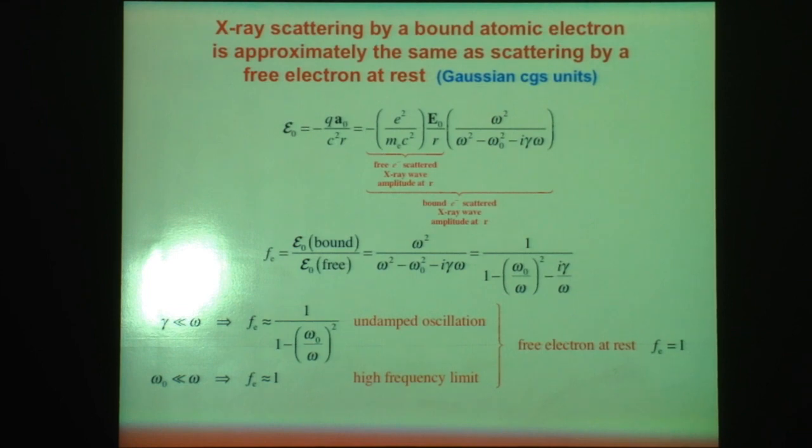Is omega the incoming frequency? That's without subscript. That's omega. Is that, in our biomolecular experiments, the case where the X-ray radiation frequency is much, much greater than the natural frequency for the nucleus electron dipole oscillation? Yes, but the important exception is the case where your biomolecular crystal contains some heavy atom, like a mercury or a lead or a uranium that's in there as a marker for trying to get a handle on the phases.